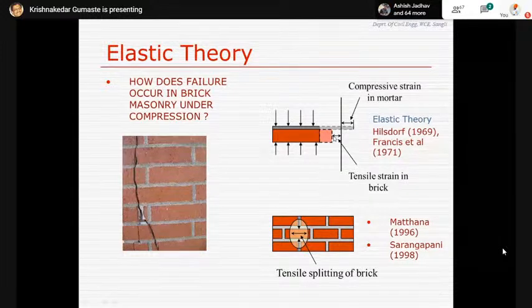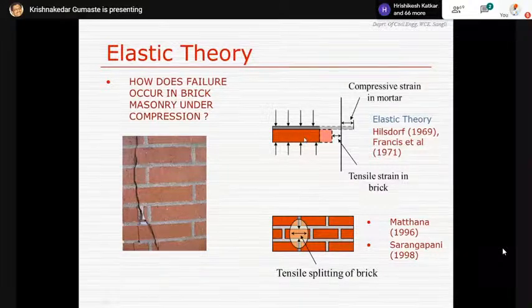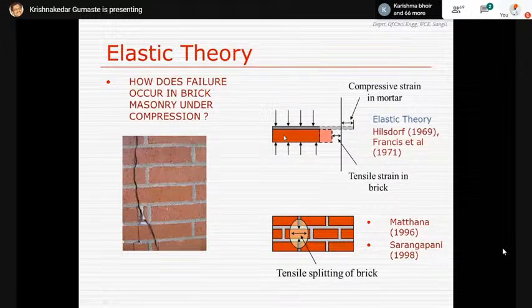And thereby, this is one of the main reasons why in brick masonry you don't see any kind of crushing unless the compressive strength of the brick units is very, very low. But most of the failures in brick masonry are basically due to splitting tension. And this splitting tension is because of the tensile strain in the brick, basically because of the difference in the elastic moduli of the two different materials that we use, the mortar matrix and the brick. It is very important to see that the elastic moduli of the mortar and the brick are matching. In Indian conditions, where the bricks are of very, very low elastic modulus and the cement mortar 1:6 gives you 9000 megapascal, a reverse kind of situation also may occur, unlike in the majority of countries. So this is the basic fundamental of how elastic theory can be applied in certain kinds of brick masonry.